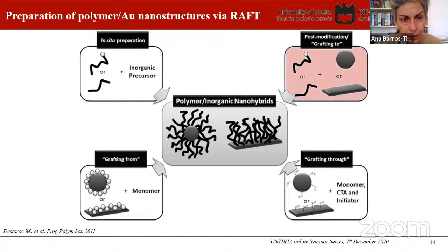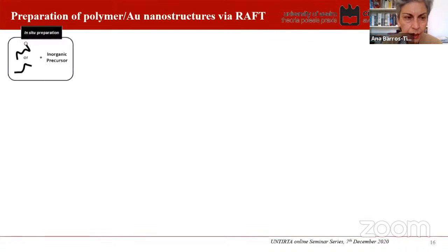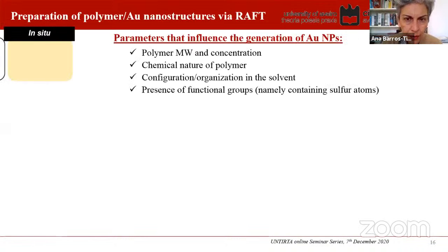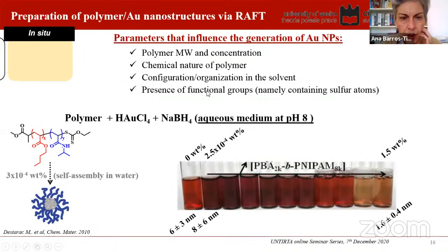So with that, we looked into the literature and tried to see what had been done and what parameters would influence the generation of these gold nanoparticles. So in this approach, we were looking at the preparation in situ of the gold nanoparticles after preparing our own polymer. So we looked into the literature, as I said, and saw that others had already looked into that, but